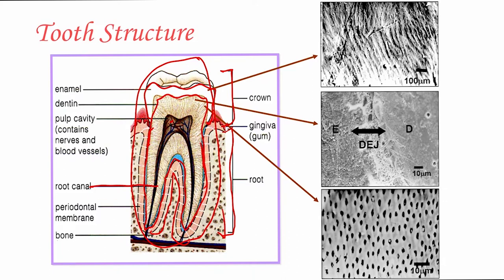One of my former students has done careful analysis of the microstructure and properties of natural teeth. He took lost teeth from several patients of different ages. This is the microstructure of an adult person's tooth — at the crown you can see typical enamel-like features. If you take a cross-section and go from enamel to dentine, you have the DEJ, the dental enamel junction, and this microstructure shows the dentinal tubules very nicely.